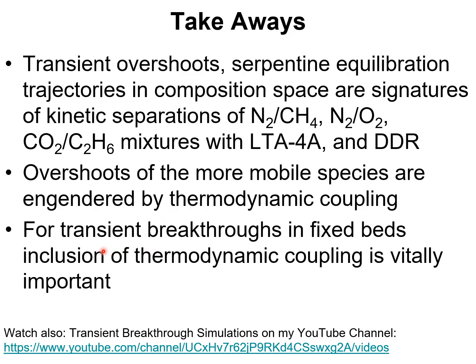For transient breakthroughs in fixed beds, we've also established that the inclusion of thermodynamic coupling is of vital importance in the determination of the productivity of the purified product exiting the fixed bed adsorber.